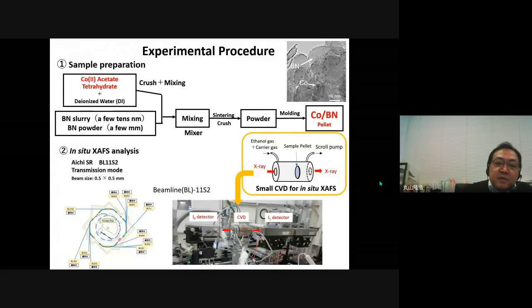This shows the experimental procedure about the sample preparation for cobalt catalyst. Cobalt acetate tetrahydrate, boron nitride slurry, and boron nitride powder were mixed and sintered. Then they were molded to form cobalt BN pellet. In situ XAFS analysis was performed at beamline BL11S2 of Aichi Synchrotron Radiation Center using a transmission mode. This shows schematics of experimental apparatus. We set a small CVD system at the beamline for in situ XAFS analysis.